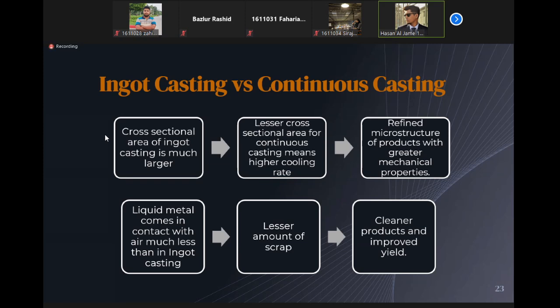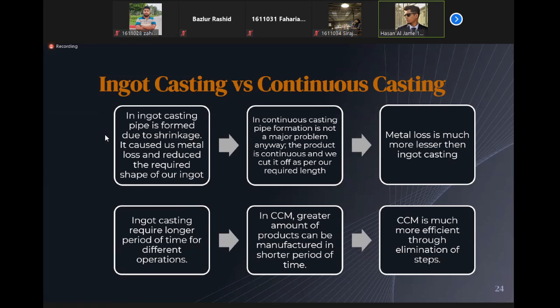Then the liquid metal comes in contact with air much less than in ingot casting, and as a result, fewer inclusions are formed in continuous casting, and less scrap is generated. So the product is comparatively cleaner, and the cleaner the product, the greater yield we can easily achieve from continuous casting. Then one of the major problems of ingot casting was the pipe formation due to solidification shrinkage. It causes metal and energy loss mainly, but in the continuous casting process the pipe is not formed, and we cut the product off as per our required length, and as a result metal loss is much less than in ingot casting. In continuous casting metal loss is the minimum. Ingot casting also requires longer time for different operations, but in continuous casting, a large amount of products can be manufactured in a short period of time. So continuous casting is more efficient than ingot casting.